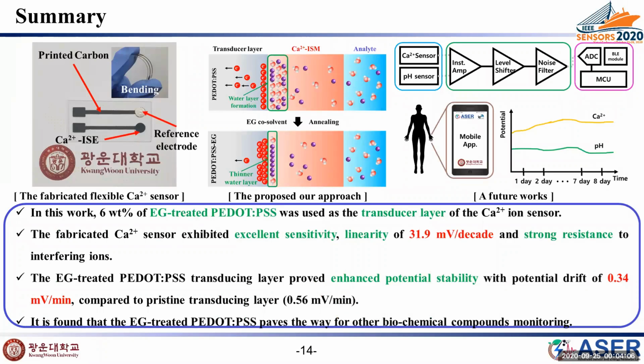We successfully developed and tested the EG-treated PEDOT transducer layer for a potentiometric calcium ion sensor. The fabricated sensor exhibited excellent sensitivity, linearity, and strong resistance to interfering ions. And also, the EG-treated PEDOT transducing layer showed enhanced potential stability, but it still has a drift. Finally, it is found that simple treatment of PEDOT paves the way for highly stable and reliable ion sensors for long-term monitoring. In future work, we will hybridize it with a pH sensor and develop a real-time monitoring system in real samples.